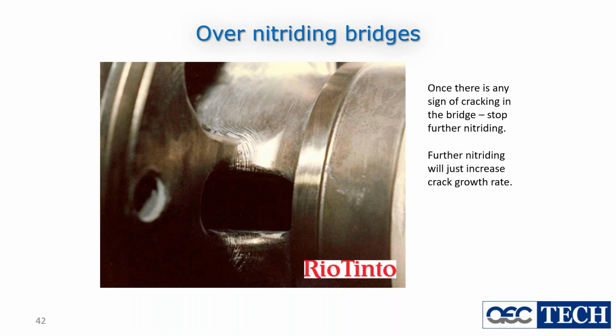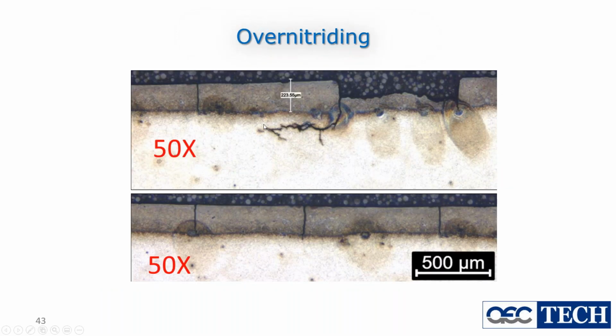So once you start getting cracking in a hollow die on the bridge, and thank you to Rio Tinto for use of this picture, those cracks will grow much faster if you continue to nitride the mandrel. By all means, nitride the die plate. But long before you have any wear out issues, these cracks will grow to the point that the die no longer works.